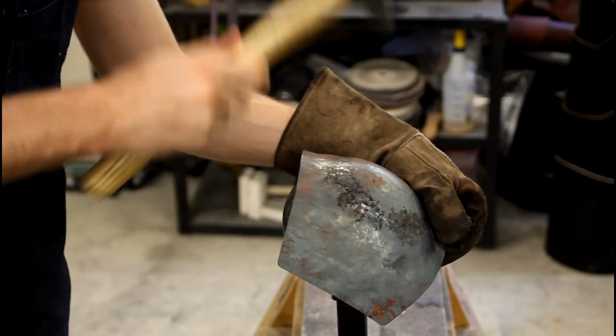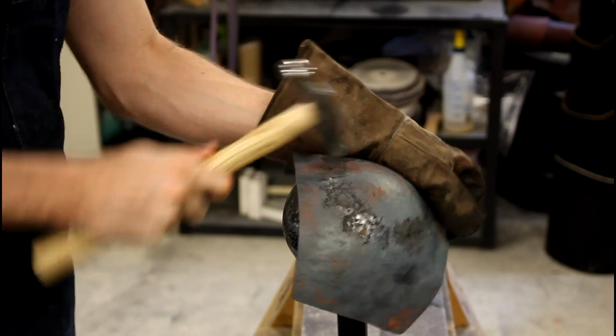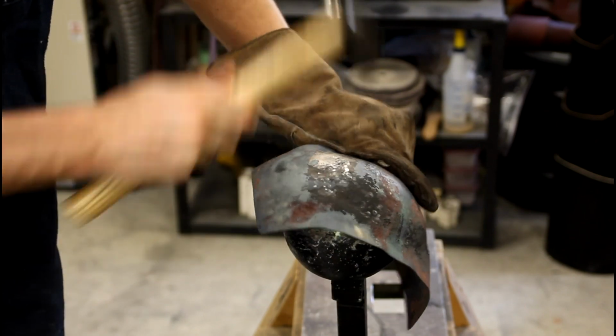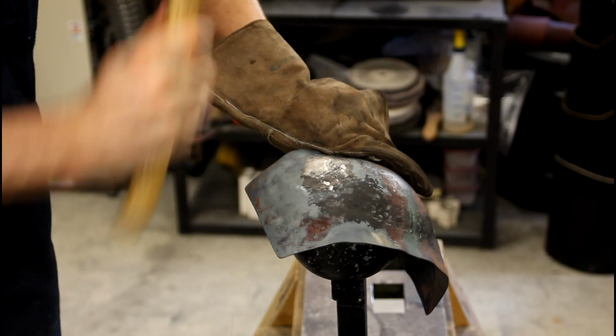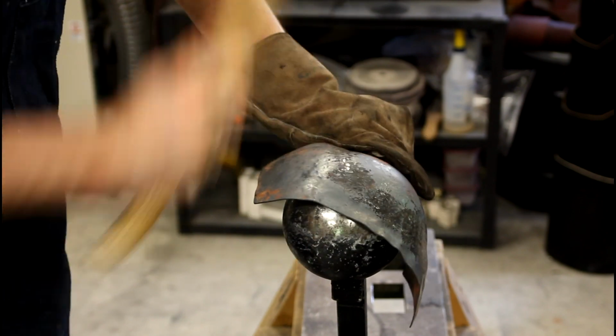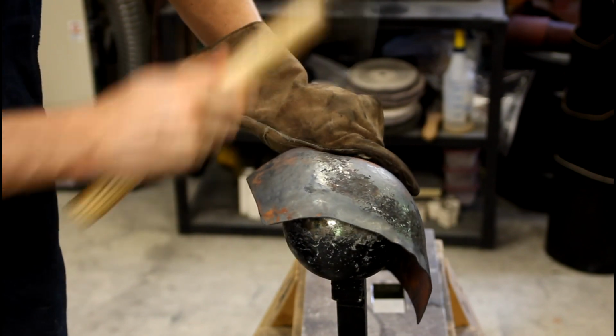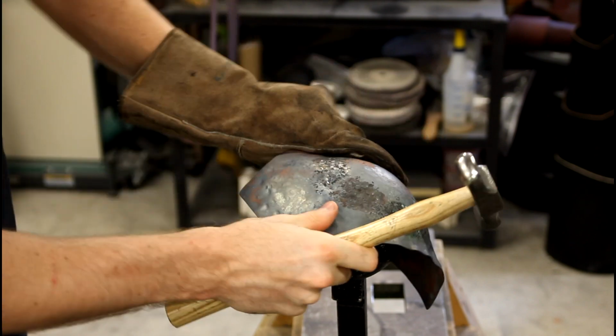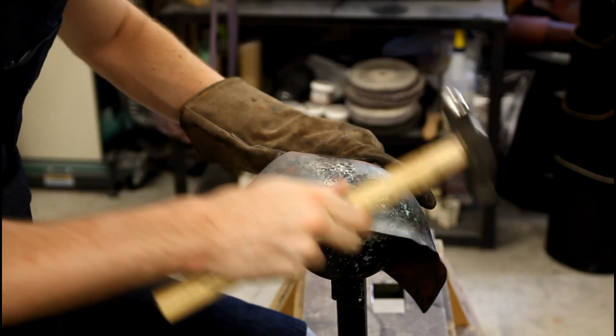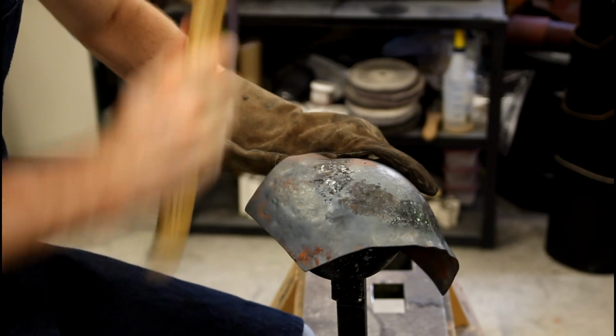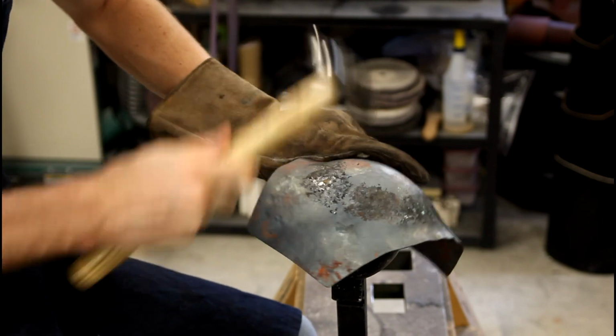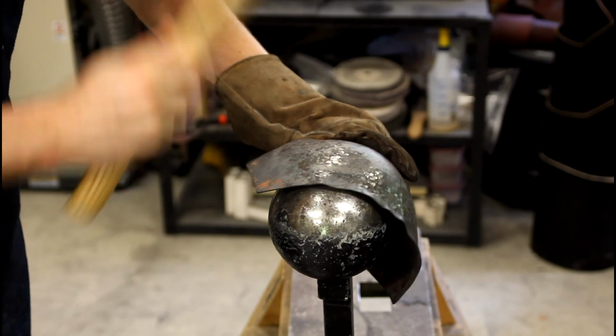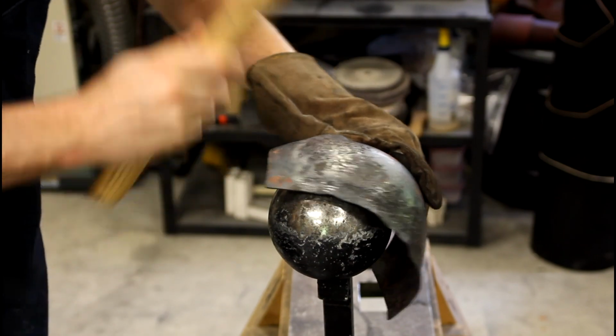Now as for the raising itself, a special raising hammer is used to strike just off center of the point of contact on the ball stake. If you look carefully, you can see this creates a wave that moves down the metal as we form the piece. Now by varying the size and the shape of the hammer, the spacing of the hammer strikes, and most importantly the angle of the piece in relation to the ball stake, you have very fine control over the curvature of the piece. Most importantly, it allows you to make asymmetrical shapes, which is something that's very difficult to do with just dishing.